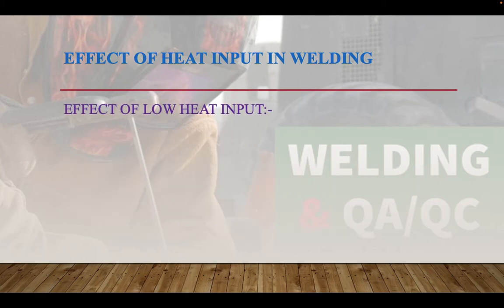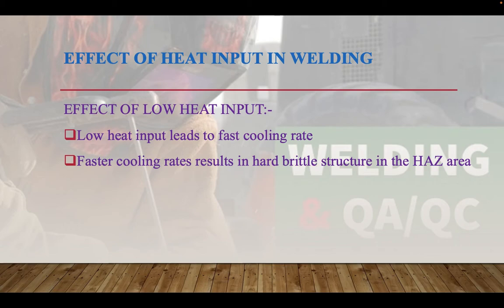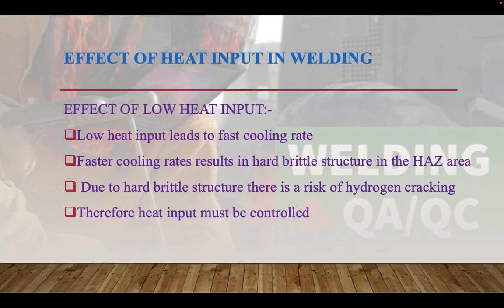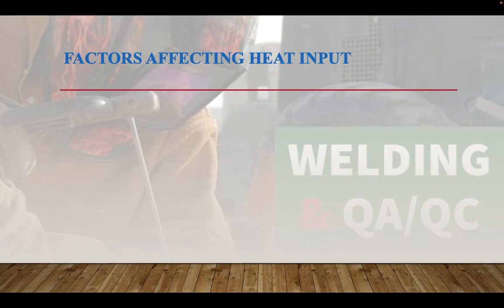For low heat input, it leads to a fast cooling rate. A faster cooling rate results in a hard, brittle structure in the heat-affected zone. Due to this hard brittle structure, there is a risk of hydrogen cracking. Therefore, heat input must be controlled.